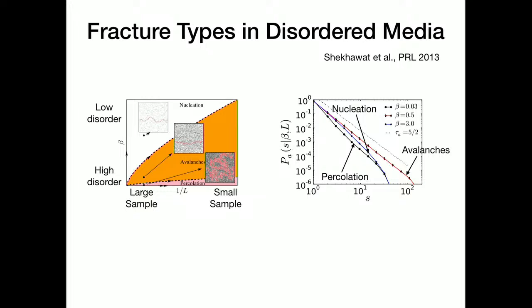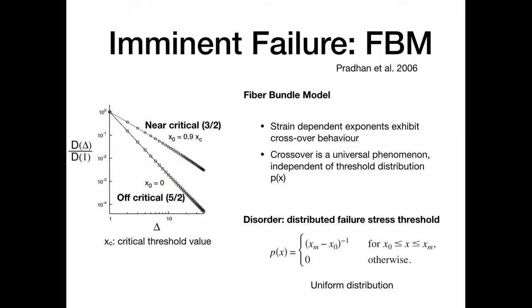This was the fracture type based on disorder. The other very interesting line of investigation is the prediction of imminent failure, because if the power law is universal, you can't tell the difference. As an engineer, we get worried about when I will know that things are going to break down, and it makes you nervous that it is not distinguishable. But these studies have shown that in the fiber bundle model, a distributed failure stress threshold is applied, and this distribution has a wide width for the off-critical exponent, and a narrow width for finding the exponent in near critical conditions.